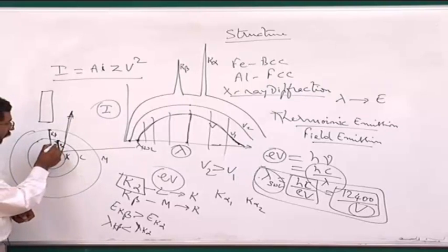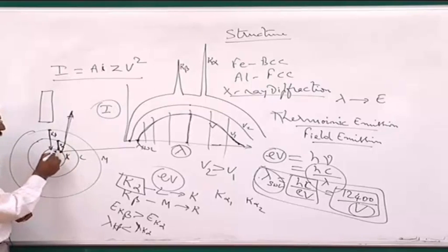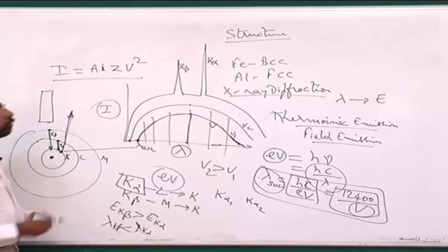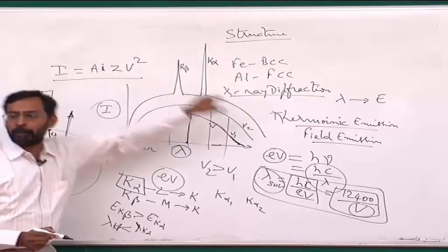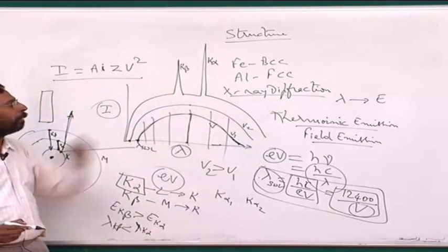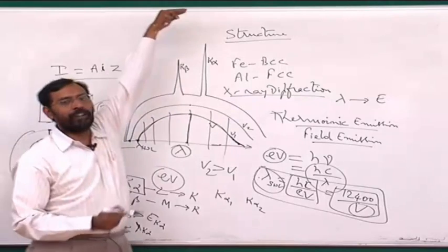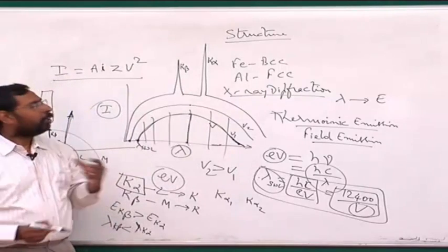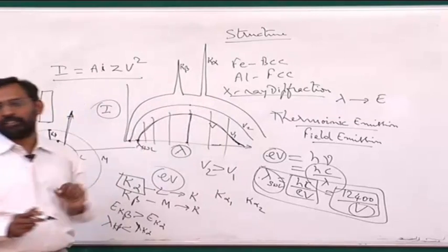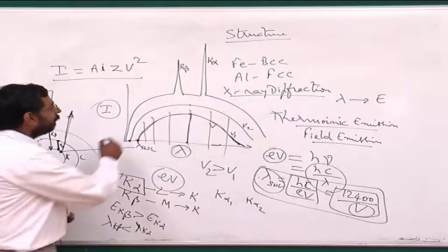So there is a higher probability that the electron falls from L to K rather than M to K. Intensities are always probabilities of finding that particular lambda. As a result, K beta will have a lower intensity and K alpha will have a higher intensity. But you always do get all this. And again, the rest of the white radiation is also there.